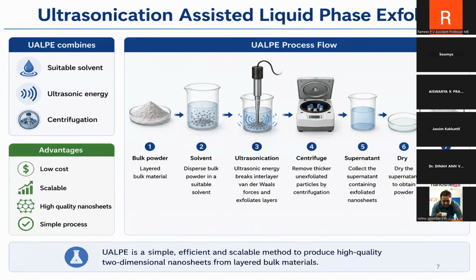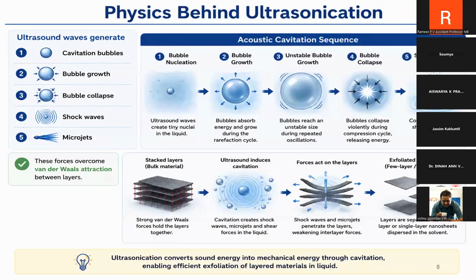So the so-called bulk nanoparticle is being brought down to nanosheets, where its nanometric dimension is brought below 100 nanometers. So this is the physics behind the ultrasonication. This is what happens when you ultrasonicate the particulates inside the solvent. When the particle is kept inside the solvent and probe sonication is carried out, you know that the ultrasonic sound waves will create tiny bubbles inside it.